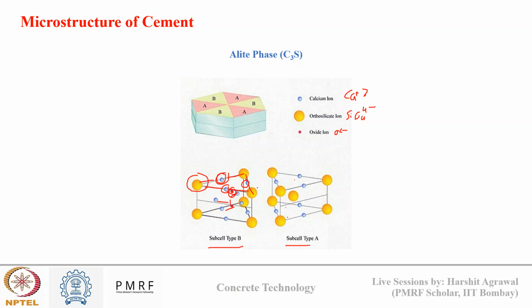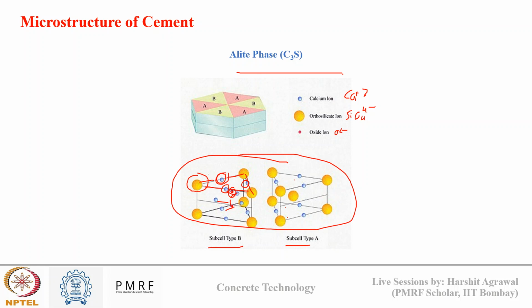So like this, the structure of calcium alite is a little complex. It is not very oriented, it is distorted and it is imperfect in nature. There are multiple sites which are amorphous in nature, and they have poor packing at the structural level, which makes C3S unstable, and that's why it is formed at very high temperature, and that's why it is more reactive towards water, because it is still unstable. It is not perfectly balanced, it is not perfectly oriented, it has multiple orientations, multiple structures present in its nature, and that is the reason why it is formed at very high temperature and why it is very reactive towards water.